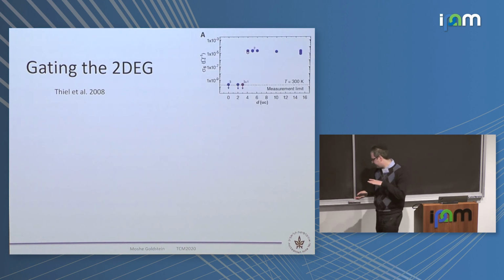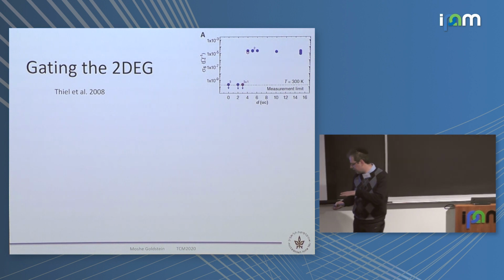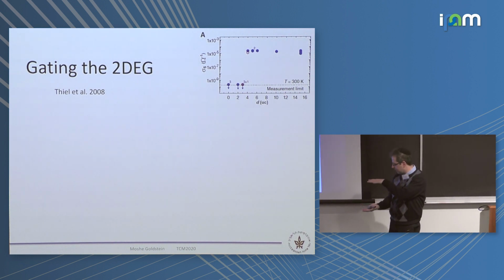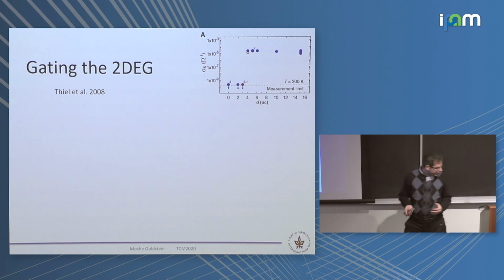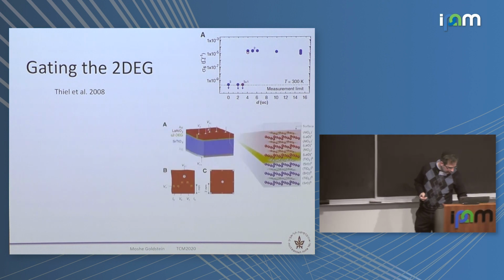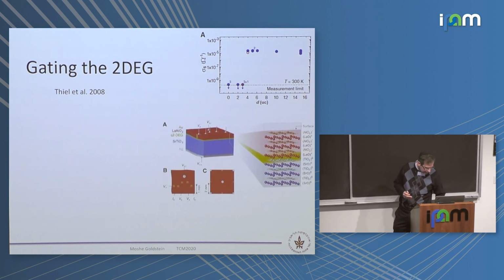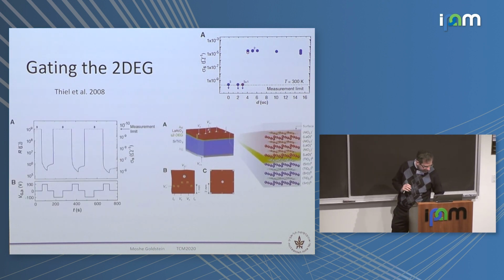it's a 2D conducting layer, and then you can put some gate on top or on the bottom and use an electric field to control the electron density, and all the properties of this interface can be controlled continuously, not by changing composition, but by applying a gate. So you can control the conductivity in situ and think about devices.